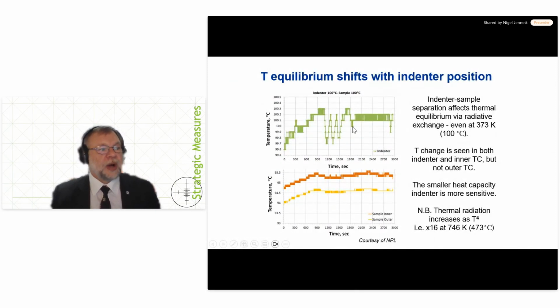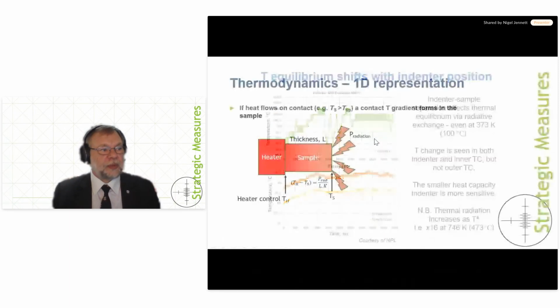This is moving backwards and forwards about 50 microns, I think. And you can see that there is quite clearly a change, which the inner thermocouple can just about see. The edge thermocouple doesn't see it at all. And therefore you can see this radiative effect actually happening quite readily with a simple thermocouple.